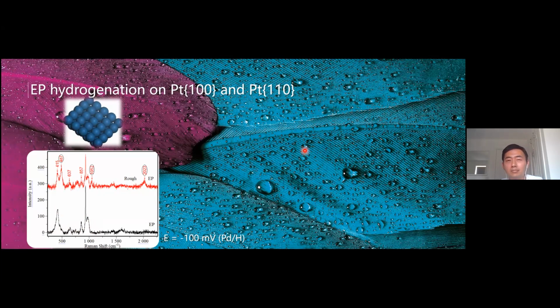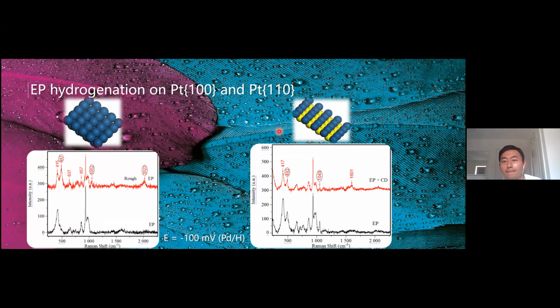What do you think of 110? Well, because the 110 surface is quite different from the previous two, even on a very clean surface there could be missing rows, causing defect sites. Therefore, both the half hydrogenated state and the precursor appear on the 110 surface.